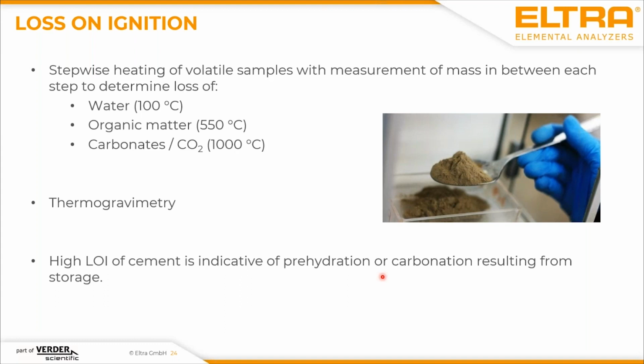Then we have organic matter. I come later to this again, the so-called TOC or other things which can really burn in an oxygen atmosphere. And then we have the carbonates coming, for example, from our limestone, which is not exactly at 1000 degrees centigrade, but it starts somewhere beyond 550 degrees. And losing the CO2 will also result in a loss of weight of the sample.